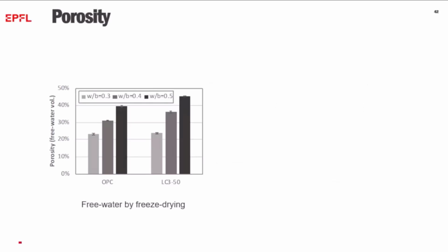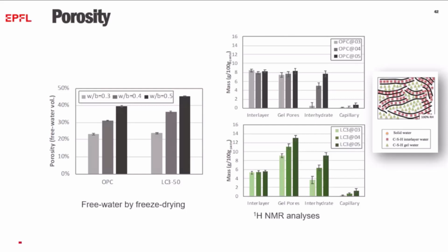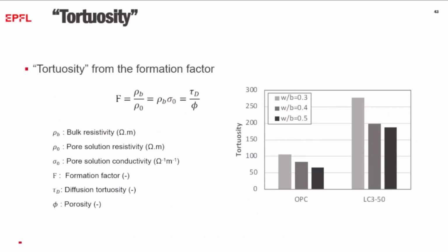And we looked and we said, well, is this related to the porosity? We calculated the porosity by the free water by freeze drying. We see no particular difference. If anything, the LC3 has higher porosity. We then did a detailed study by proton NMR. Again, we see if anything, the calcined clay has got higher porosity. So why does it have lower chloride diffusion?